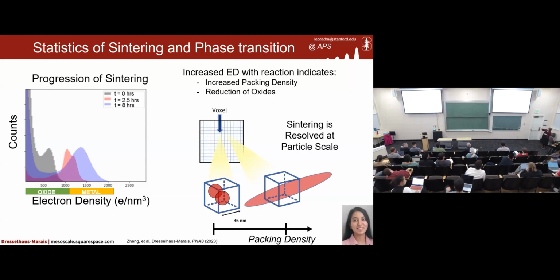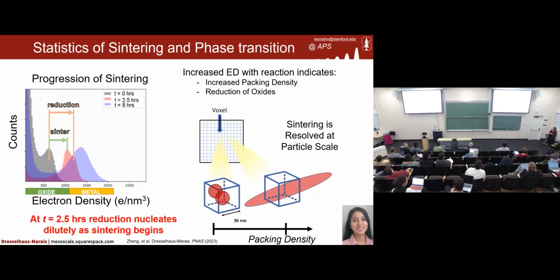So you'll notice here that if we look now at a histogram, looking at all the different voxels that make up the different samples from our interrupted run, we end up now with, at t equals 0, fully oxide. At t equals 2.5 hours, we have a bimodal distribution. But you'll notice the first mode is showing us a higher density oxide, i.e. it's showing us that we have sintering. The second one is now showing us that we formed some of the metal within each of those voxels. So this is demonstrating to us that at 2.5 hours, we start to have the nucleation and growth of a metallic phase, as we also are sintering our oxide. So this is characteristic of that sticking I mentioned before at the reactor scale.